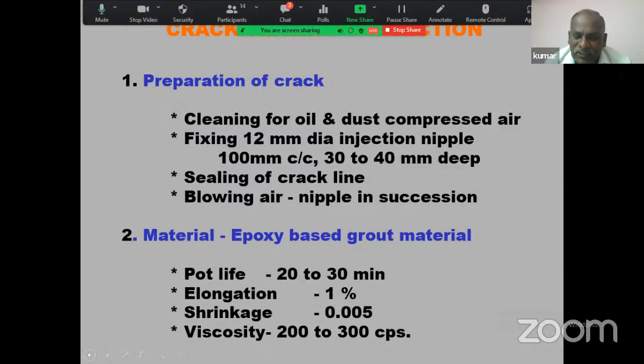For that, the pot life is 20 to 30 minutes after adding the curing agent, elongation is 1%, shrinkage is very less, viscosity 200 to 300 centipoise. So low viscous epoxy is selected for the grout material. This is what we have recommended for the Chennai Port Trust.